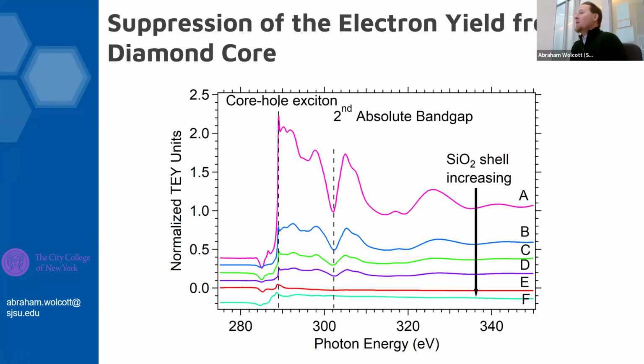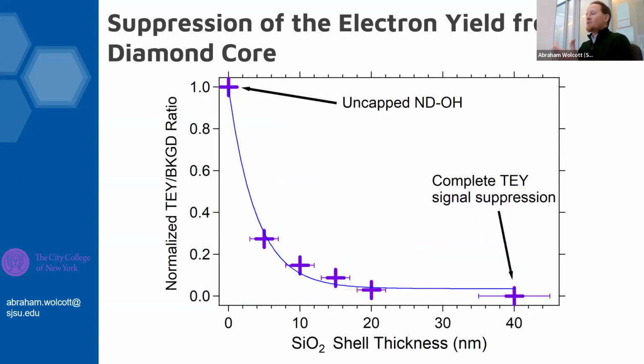So we wanted to be able to readily change that silica shell because we wanted to put them into cells and control the endo and exocytosis rates. And in the process, we ended up seeing that our diamond XAS spectra, this fingerprint spectra, would readily change. The thicker the shell became, the less diamond information we would get. And as we go from A, B, C, D, E, and F, we end up completely suppressing the information from the diamond core. And the question is, well, how far into the diamond can we look?